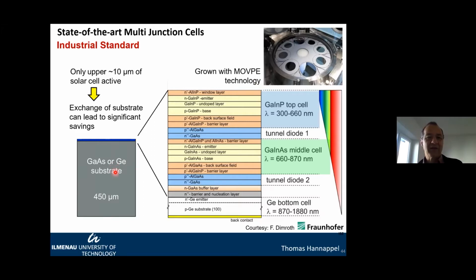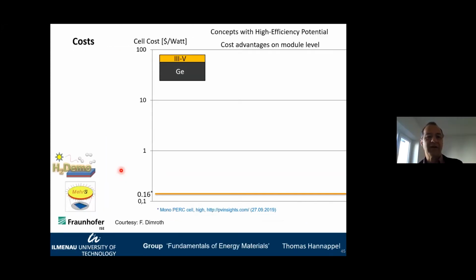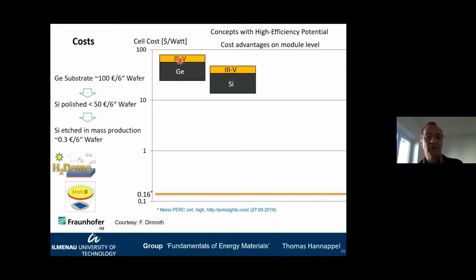And so this is, of course, one part of this cell, which should be replaced by a much cheaper one, which would be, for example, silicon. And that you can see here. You see that the cell cost right now for such a high efficiency cell is way too expensive. So what we would need is, of course, to be much cheaper, like 2 orders of magnitude. And then you can see that one huge step would be, of course, the replacement of the substrate by silicon.